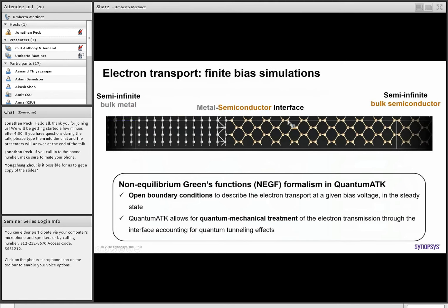So the key feature that I will use a lot in the next slides is what we call, again, this non-equilibrium Green's function formalism in ATK, which you can couple with DFT or semi-empirical, and then you can study electron transport across interfaces. Here this is just a model of a metal-semiconductor interface. You see this is silver, these atoms here, and these atoms here represent silicon. And we have a central region which is coupled with the semi-infinite bulk systems.